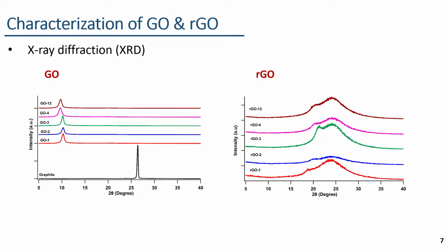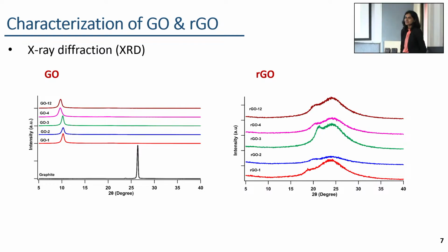So graphite has the crystalline structure, but reduced graphene oxide is a more amorphous structure. But the graphene oxide's XRD peak was situated near the peak of the graphite, right? No, graphene oxide is at a lower diffraction angle, around 10. Graphite is at 26, and RGO is in the 20s, between 17 and 30. Here we cannot observe any sharp peak, but a broad peak. So can we say the planes of RGO are similar to graphite? No, it is not similar to the graphite.